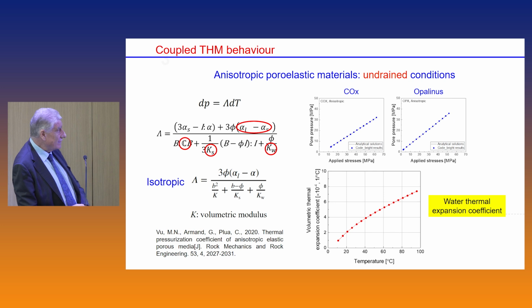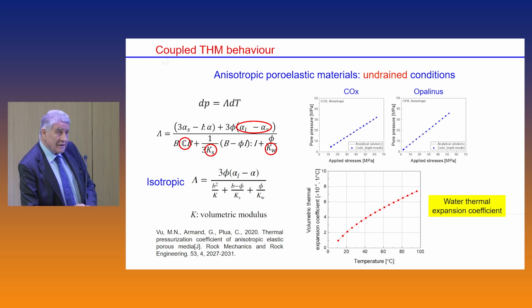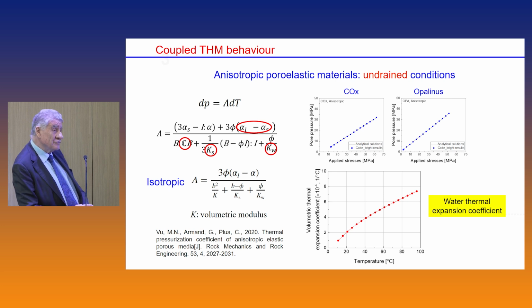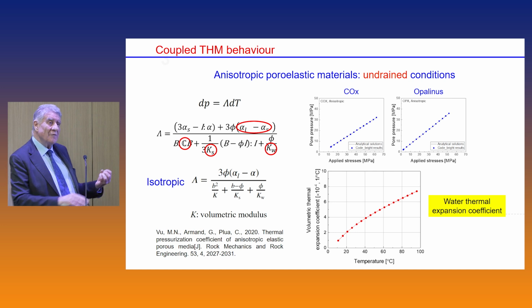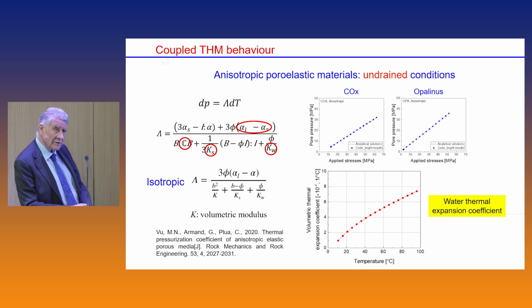If you simplify the problem and assume undrained conditions, so there is no water going in and out, actually, Vu, Armand, and Plua have very nicely derived the equation for the coefficient that relates the increase of temperature to the increase of pore water pressure, and we can see here that the usual culprits appear. This is the differential thermal expansion of the phases, the stiffness of the material, the compressibility, the volumetric stiffness of the solid phase and the water phase. And obviously you have to check your code, because sometimes there are subtle things in the codes that don't consider all these things, to make sure your code is actually giving you the right result.